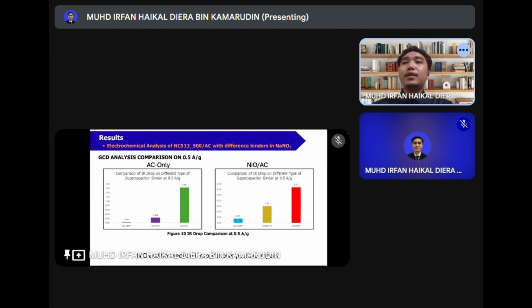However, in IR drop, it has improved significantly from 0.24 volt to 0.15 volt. This shows TS plus NiO enhances GCD performance and maintains electrical stability. PTFE still had the highest IR drop even with NiO, indicating poor conductivity.